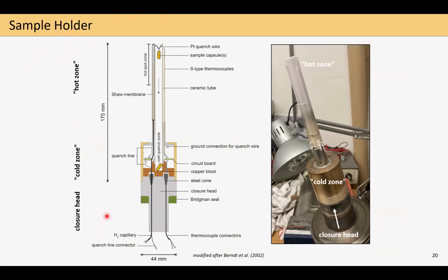So we have again a so-called closure head, which serves to get a variety of signals in and out of the vessel with these different cones. Then we have a cold zone where we quench our experiments, and we have the hot zone where the samples are located in the thermal hotspot of the furnace. Here, just also the comparison, the sketch, and the real image, how this looks like.